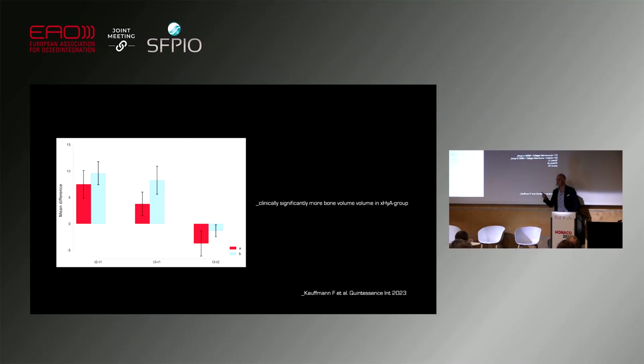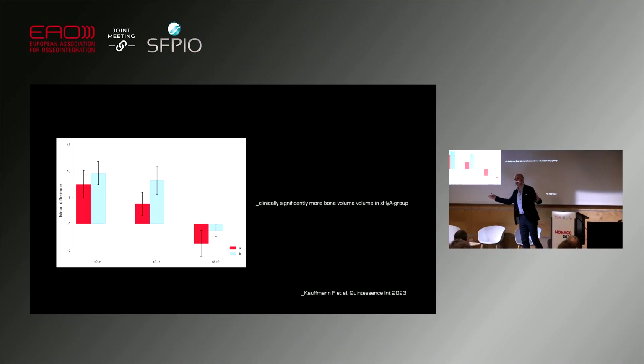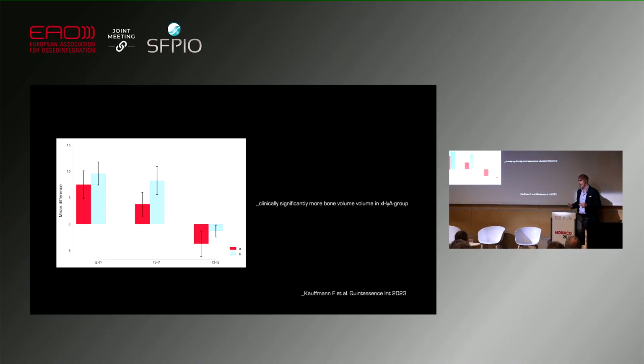From a clinical perspective, it was quite clear, very clear. Look at the data, very clear. There's significantly more bone volume in the GBR procedure combined with hyaluronic acid. Although there are fewer residual particles, there's still more bone in these cases.